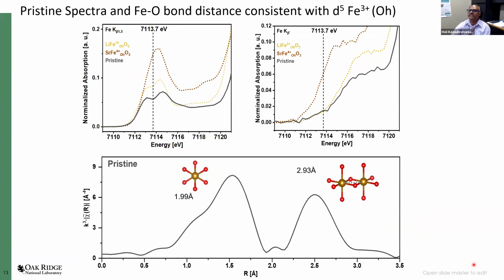So here are the pre-edges now. This is the pre-edge of LiFeO2, which is a standard for 3+, and that is the pre-edge for SrFeO3, a standard for 4+. And you can see that the pristine compound has this classic double peak structure, normally assigned to t2g and eg-like orbitals in the d manifold. Also, there are features over here which come from those non-local interactions. However, if you look at the same thing using K beta prime, you can see that the intensity going up for the 4+ is not there for both the LiFeO2 as well as the pristine compound, consistent with the iron being in a d5 octahedral situation.